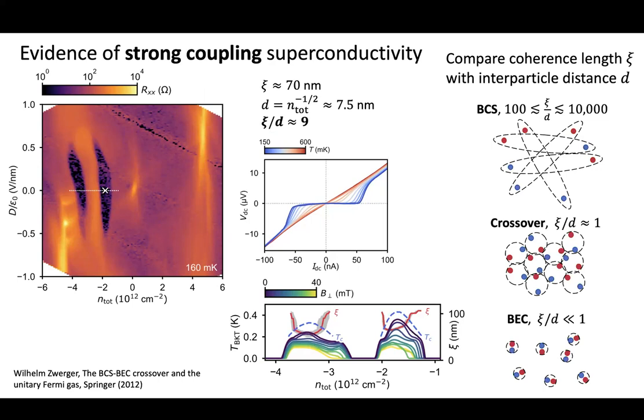In a number of quasicrystals, there have been reports on localization. We don't see that; we see highly resistive states, but not insulating states. And we think it's because some of those Dirac cones are like highways for electrons, so they're short-circuiting your system. Similar to the magic angle trilayer: the trilayer doesn't have insulating states, nor the tetralayer or the pentalayer.